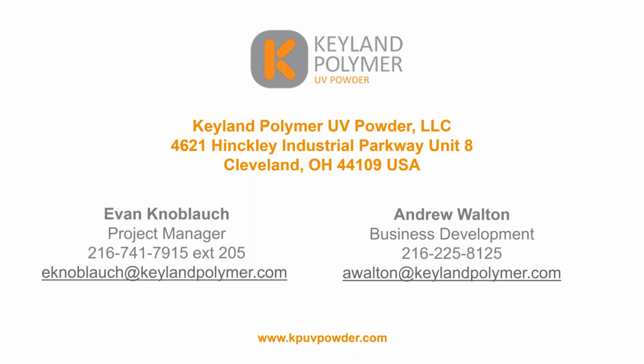If that's the direction of the question, we haven't looked much at putting a UV powder on top of a liquid finish, and we have done it occasionally here and there, but it sometimes can wreak havoc with both intercoat adhesion between the layers of finish, and then the heating process needed to gel the powder, or melt the powder, excuse me, sometimes can affect those coatings as well. So we tend to not coat on top of previously coated materials or recoat materials as well.